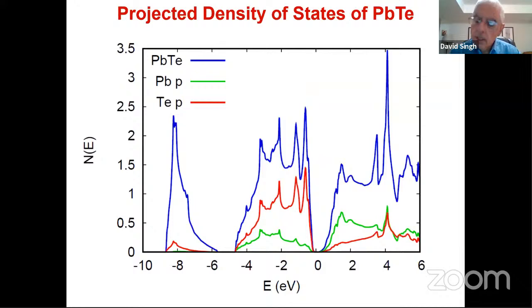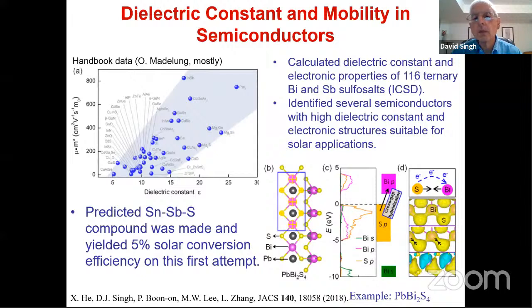So what does this mean? This means that we can expect for a certain number of holes, good conductivity in lead telluride, which is important for the thermoelectric performance. And actually, you can see there are many new semiconductors that have very high dielectric constants and are becoming quite important in technology. An example is the perovskite halide solar materials, which also have extremely high dielectric constants, and because of that have very good charge transport, which is important for their high efficiency in solar applications.